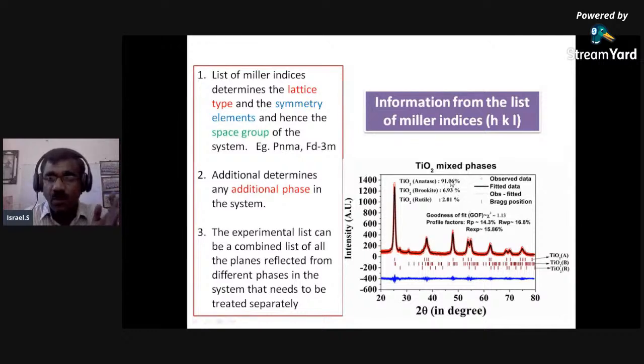See, 91.06, 6.93%, you can find out these numbers, how much percentage is actually there, by looking at the HKL in Miller indices. See, these reflections are basically Bragg reflections of the anatase phase. This is for a brookite phase, and this is for the rutile phase. Once you accommodate all these phases, only then in any powder refinement, we call that a Rietveld refinement, you'll get the small error.